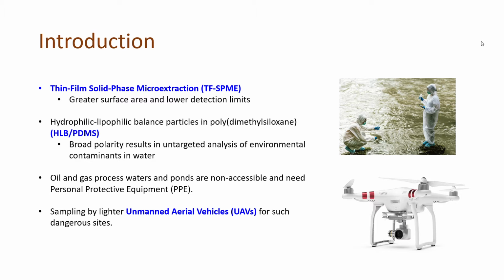The hydrophilic lipophilic balance particles and polydimethylsiloxane were used as a coating on the carbon mesh support. The advantage of the HLB PDMS is that it has a polydivinylbenzene co-vinylpyrrolidone skeleton structure, so it provides a balance of hydrophobic and hydrophilic intermolecular interactions, and therefore it is useful for broad polarity and untargeted analysis of environmental contamination in water.